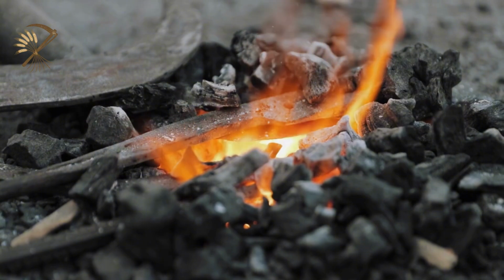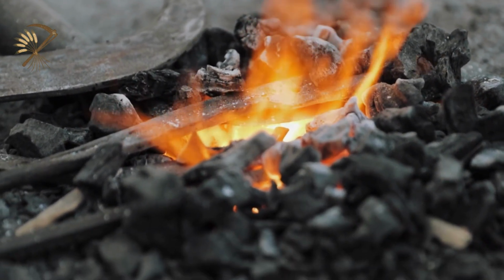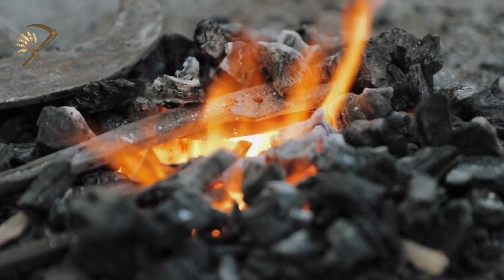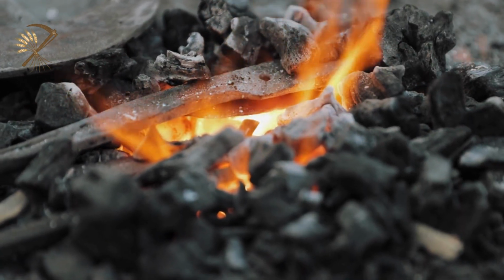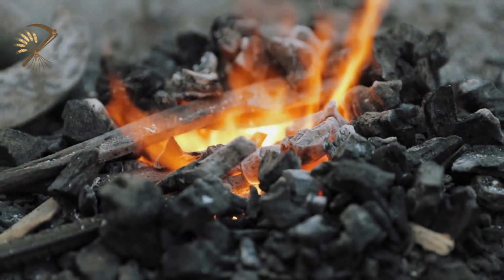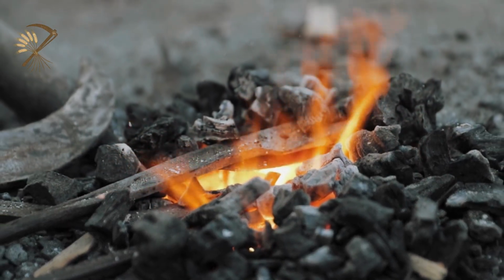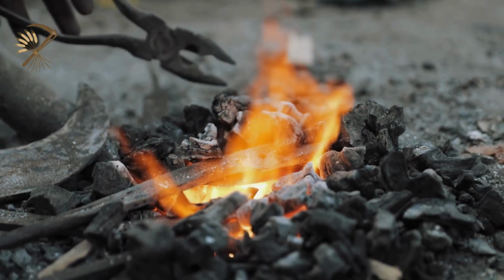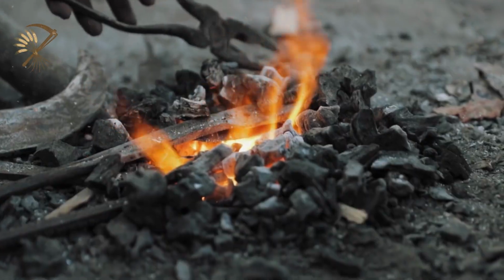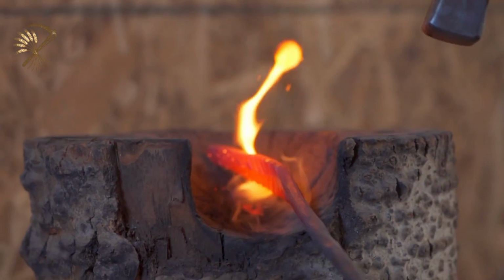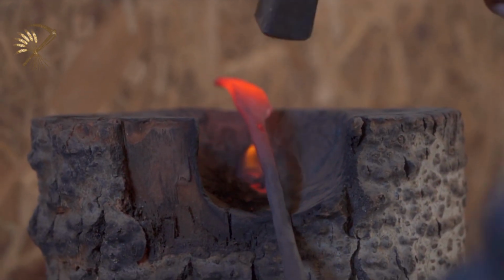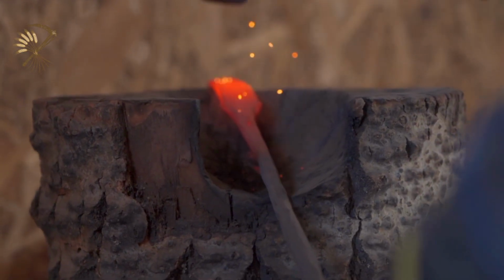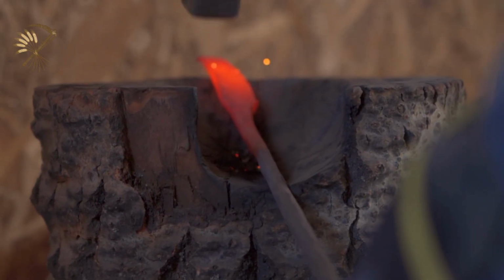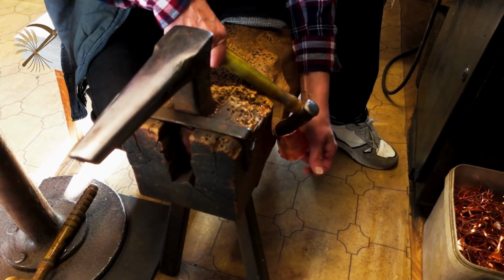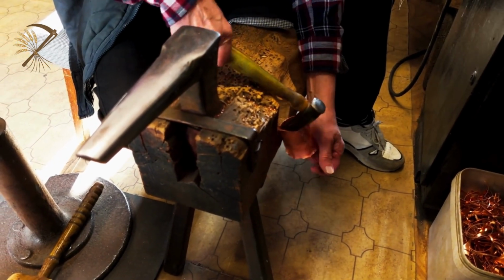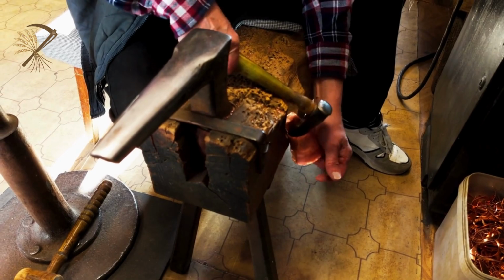The chisel requires 25 to 35 degrees depending on the material. It will cut softer, with shallower degrees for wood chisels that need razor sharpness, and steeper degrees for metal cutting chisels that need impact resistance. The draw knife uses a single bevel at 15 to 20 degrees for maximum sharpness in the pulling cuts characteristic of shaving wood. Modern factory tools are stamped or ground to nominal angles that often deviate 5 to 10 degrees from specifications due to the speed of production.